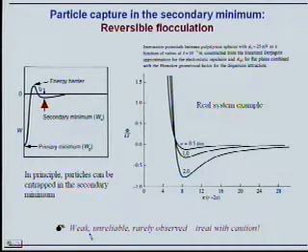So numerous researchers and writers of proposals, especially these days when everybody tries to do something on the nanoscale, have tried to make use of this secondary minimum. You can write it in a proposal, but then it's not likely to work. So this is really something that theory predicts, has been observed in some rare cases, but it's not a really stable and serious entrapment of particles.